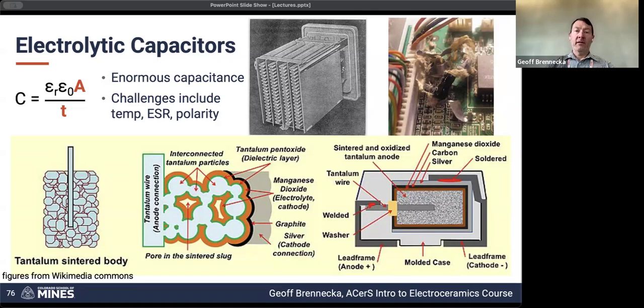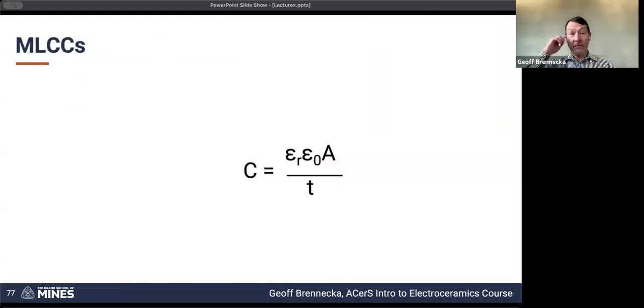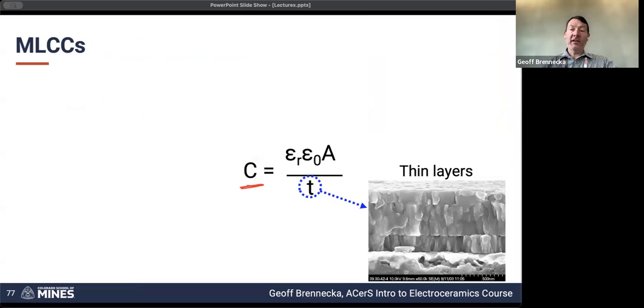If we want to compete with these relatively simple, we're just going to oxidize the layer of our electrode. We're going to get more clever with multi-layer type technologies. So if we want to make a multi-layer ceramic capacitor, we need to, within the constraints of whatever operating voltage and frequencies are, maximize capacitance. So we can start by making the thickness as small as possible. So we can make very, very thin layers. There are massive practical challenges to this. So for example, you need to be able to tape cast a layer that's less than a micron thick, and you want multiple different grains within that layer for reliability concerns.